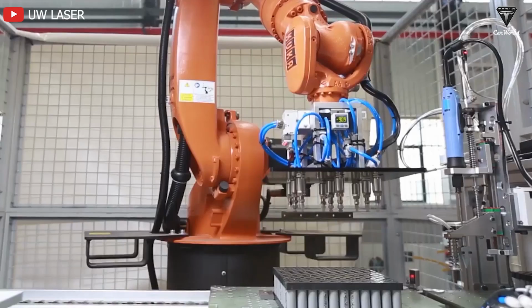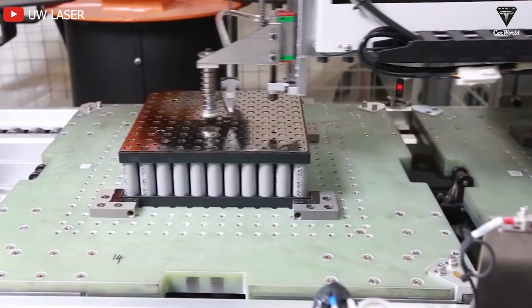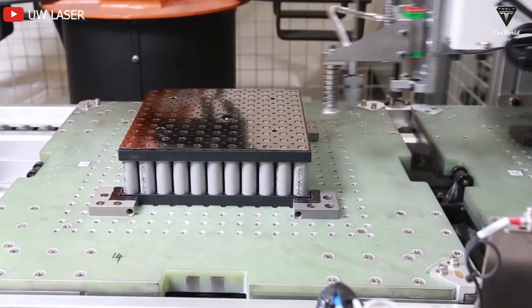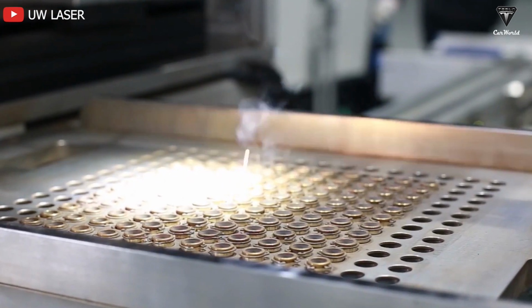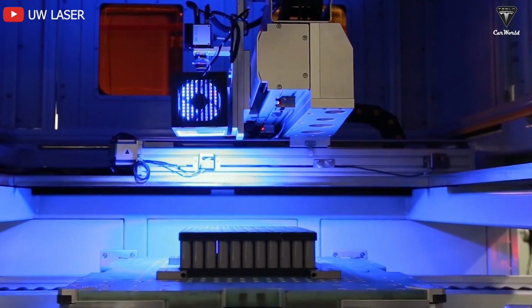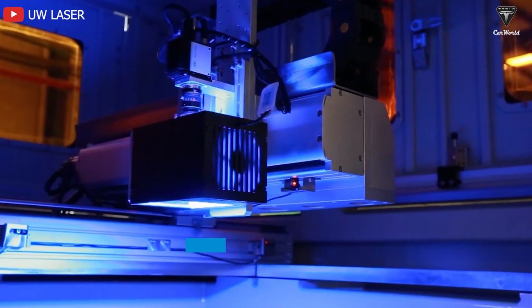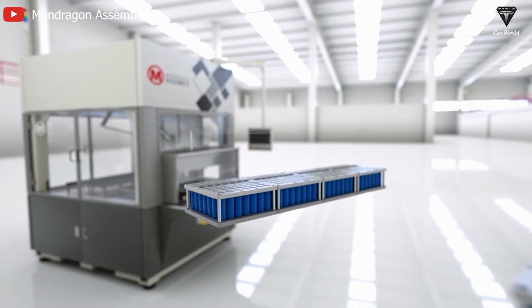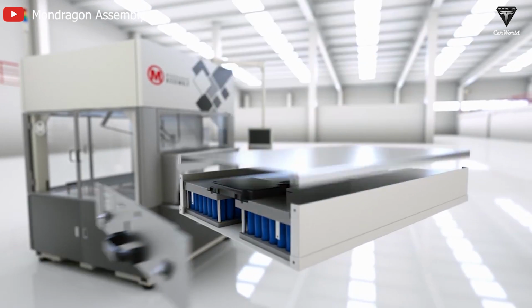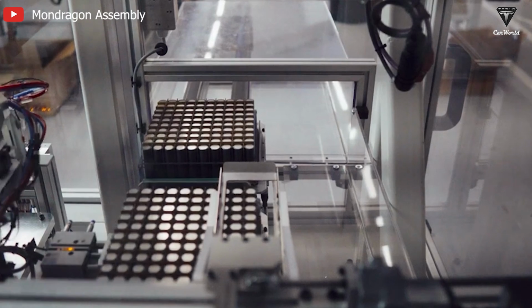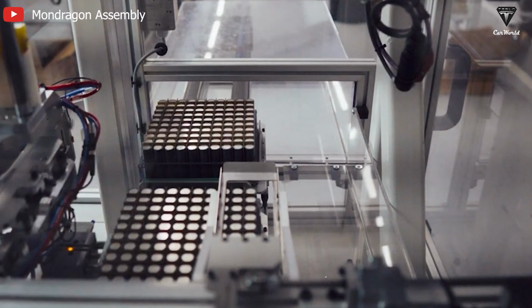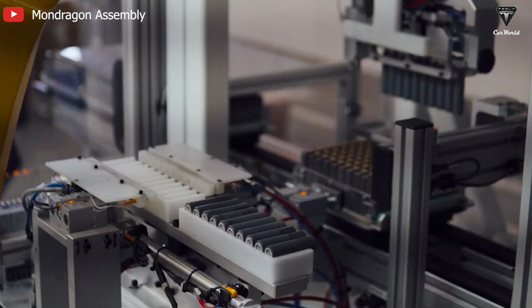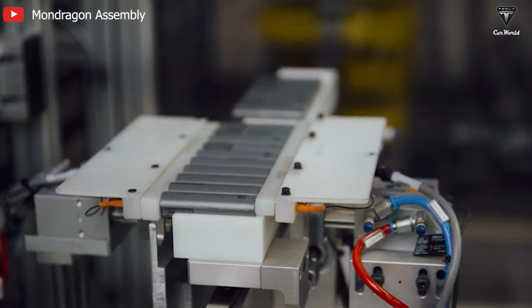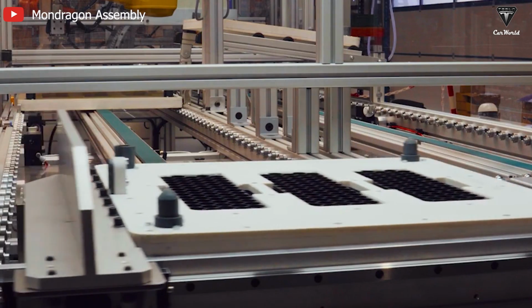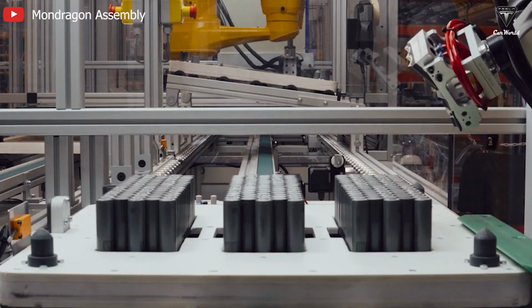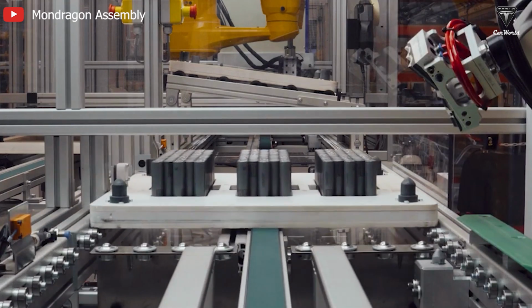Lithium-ion batteries are also slightly more efficient when it comes to using the energy stored in the battery, as they use 90% of the stored energy, compared to sodium-ion's 80 to 85%. Lithium-ion batteries are also more efficient when charging. They charge faster and can withstand more charging cycles. Sodium-ion electrodes suffer structural deterioration during repeated discharge cycles, typically about 3,000 cycles, while lithium-ion chemistry used for off-highway applications can withstand up to 10,000 charging cycles, depending on the cell chemistry chosen.